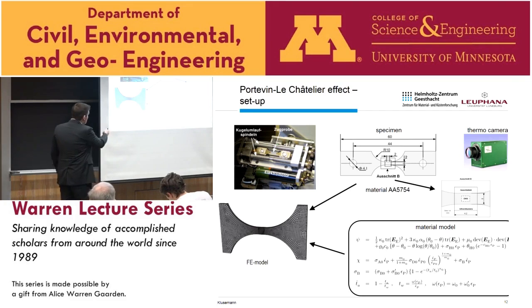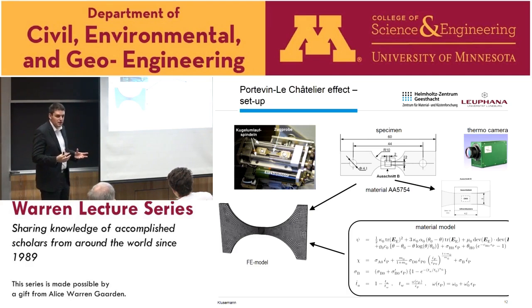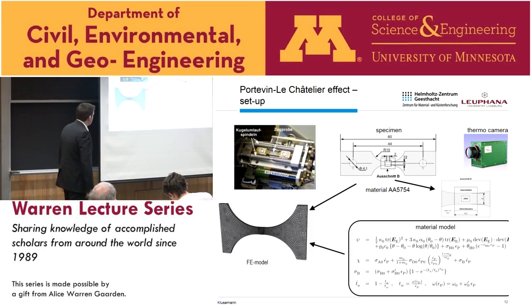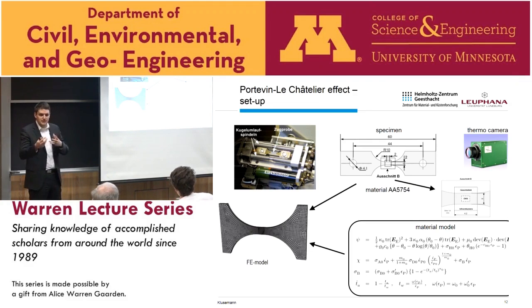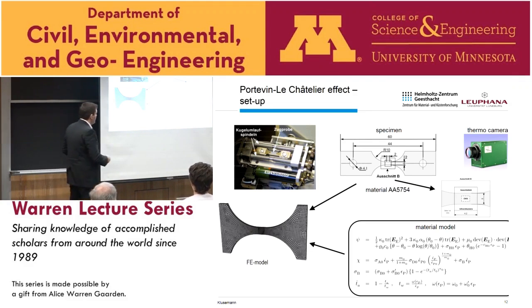From that, we set up, of course, a finite element model, a bit simplified here, and of course, we had to take care of the mesh density inside of the interesting region because we're using a local model. We don't use a non-local model, we're using a local model, so we have to take care of the mesh sensitivity. Our material model is based on continuum thermodynamics, so everything is related to energetic and dissipative effects.